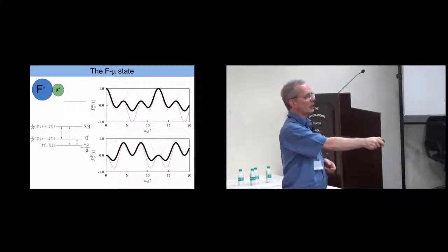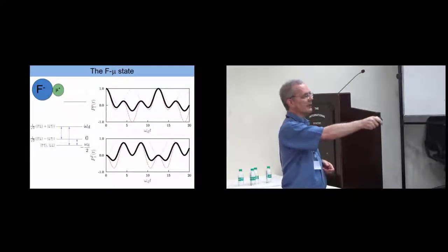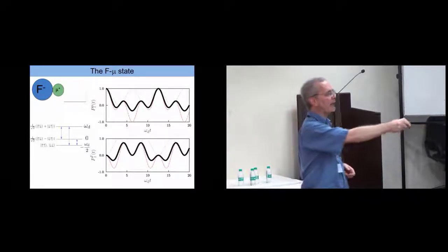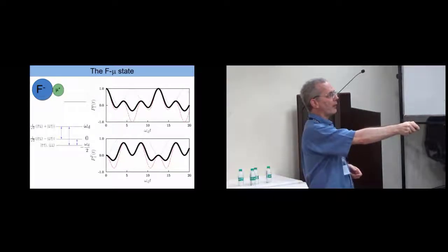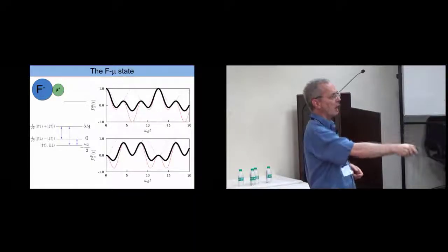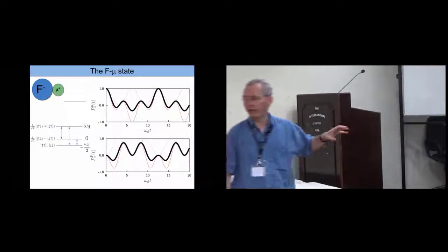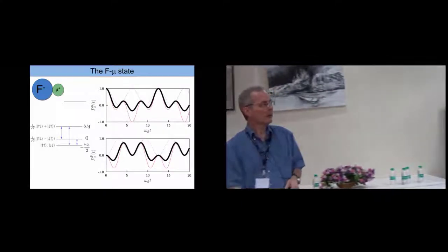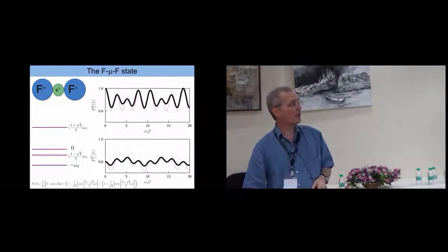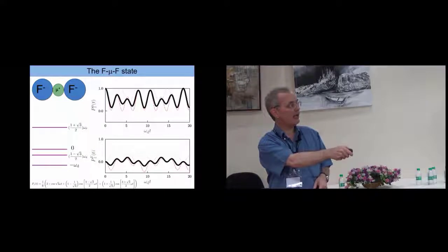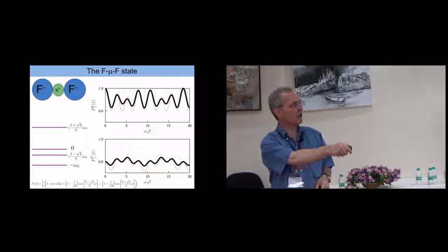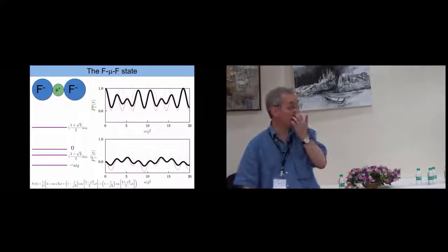these two species, you get three energy levels, and then you get these various transitions, and the black line here shows you the probability of the muon spin as a function of time. And what you can see is you get this interesting beating pattern between these different frequencies. I'm also showing you a lower panel to show what the fluorines do, but you can't measure this. Now, in fact, very often what happens in materials is you get this so-called F mu F state. You get a more complicated series of energy levels, and you get a more complicated beating pattern.